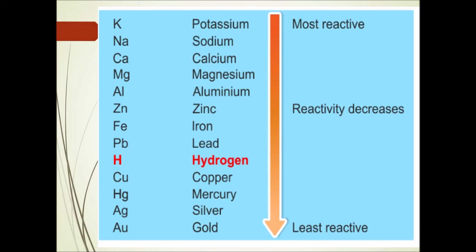In simple terms, reduction of highly reactive metal oxides is done by electrolytic reduction, and moderately reactive metals like zinc, iron and lead are reduced by adding a suitable reducing agent, which is chosen using the Ellingham diagram, and least reactive metals like mercury, silver and gold are reduced by thermal reduction.